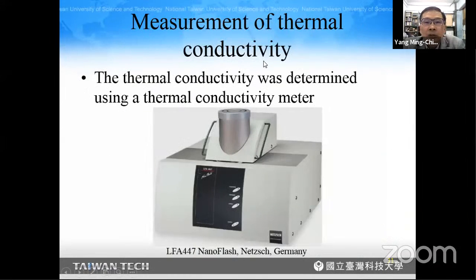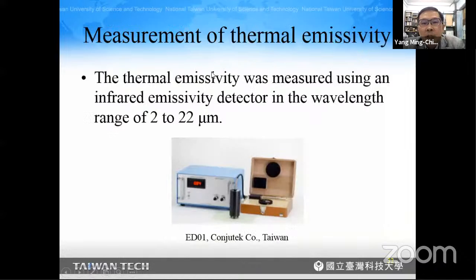Now we want to measure the conductivity of this material. The thermal conductivity was determined using a thermal conductivity meter as shown here. And the thermal emissivity was measured in an infrared emissivity detector in the range of 2 to 22 micrometers, which is in the range of infrared.